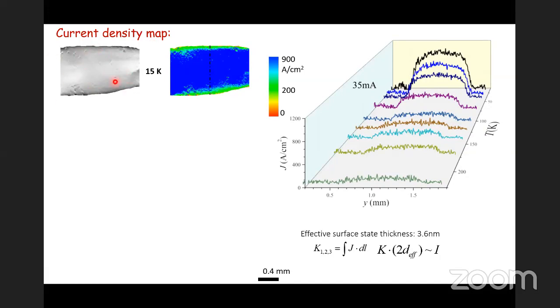This is the surface of the single crystal, and you can see the bright region is all over the crystal uniformly. If I convert this into a map of the current density, you can see that the current density is uniformly blue all across the sample surface. This is the line profile of the measurement of the current density, and the current density you can see is almost flat all across. So it is actually a 2D surface sheet of current which is present on the thin single crystal. On the single crystal, you can actually see directly the conducting surface state as a 2D sheet of current which has a very high current density.